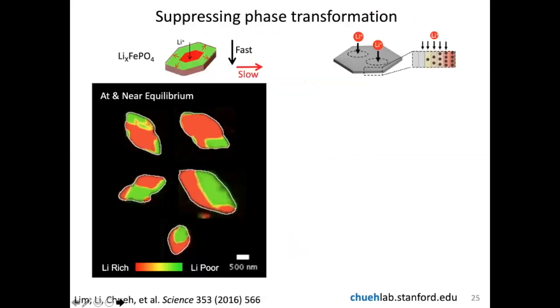So I'm a bit out of time here. I would just end with this one slide. The observation that phase transformation depends strongly on the rate not only occurs at the many particle level, it also occurs at the single particle level. So here I'm showing you an image of the phase separated lithium iron phosphate at half lithium content, so lithium 0.5. And you can see the beautiful phase separation into lithium rich and lithium poor region.